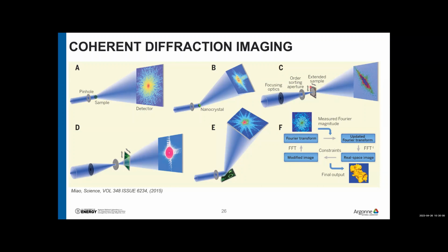So that you have a very large extended field of view rather than a single point. It's called ptychography. You can use that in reflective geometry to have access, for example, to the nanoscale strain in a flat sample. And so this is really a game changer for a lot of the experimental measurements that we do and we will do at the upgraded APS.